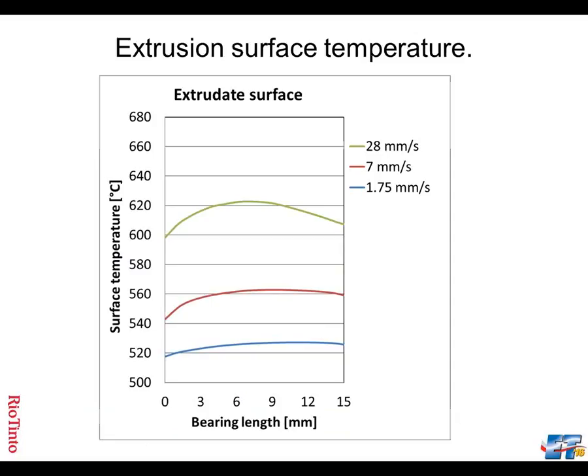Just to give you a couple of other illustrations, what can we predict? This shows the surface temperature in the bearing. It's a 15mm bearing for this profile. And you can see that the temperature is obviously hotter as you extrude faster. The maximum temperature is in the middle of the bearing.